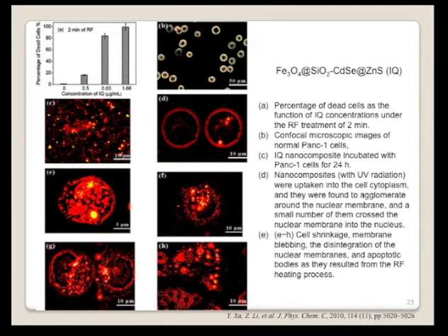That's image E of this process. Once we turn on the RF, at different times we take the image. In the first one you can see the cell apparently shrink. The pancreatic cell's diameter is around 20 micron, and here it is just about 10 micron. First the shrink. Okay. Then you can see some